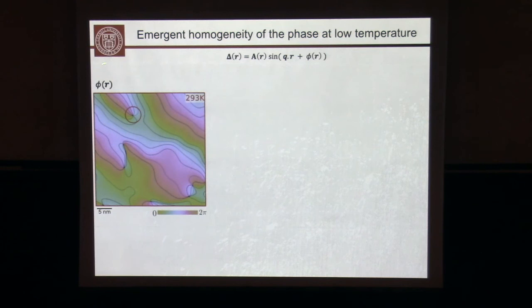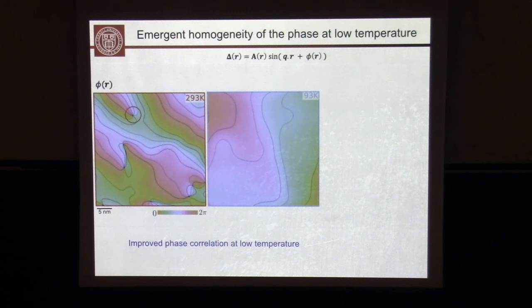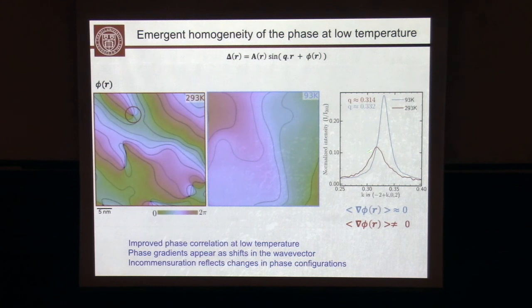Here is one example where you have a phase wrap of 2 pi. This is a topological defect. And these are examples of shear disorder, the same things that I showed you at higher magnification earlier on. At room temperature, there's lots of phase disorder. When you cool, you see much improved phase correlation, a much flatter phase field. That picture of stronger coherence in the phase is consistent with the shift that we observe in the K vector, because if the gradient of the phase is non-zero, you get a shift in K. So what we believe happens is that the incommensuration you see in diffraction reflects changes in the phase configuration of your sample, so all local displacements.